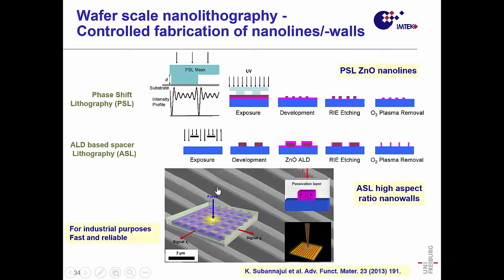Okay, let's go to another way. We found actually, maybe for sensors, it would be much better instead of the nanowire to use what I call nanowalls. And they're using these lithography things. They're a rather cheap and reliable way to grow these nanowalls. So what you need is, again, such an exposure, this phase shift lithography, what we have here. And then we have two processes here.